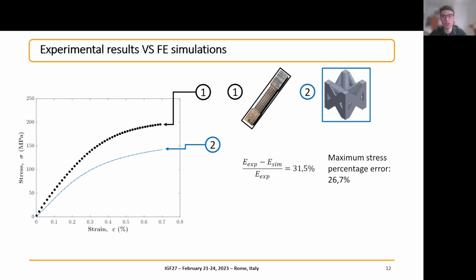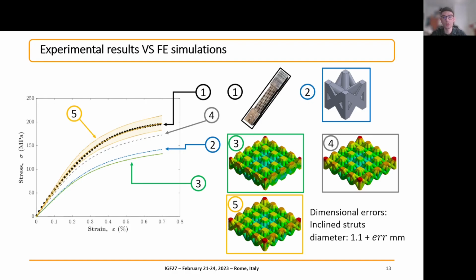So to improve the simulated response, we decided to model the response of the lattice structure with a lower degree of approximation, but of course a higher computational cost. So basically we simulated the response of a full section of the structure with 16 cells. For example, in case number 4, we also modeled the struts with full diameter at the boundaries, and as you can see, the macroscopic response is much closer to the experimental data,